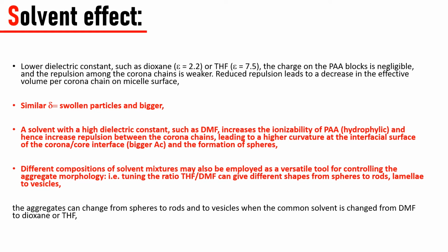However, a solvent with a higher dielectric constant, such as DMF, leads to an increase in the ionizability of the polyacrylic acid, increasing the repulsion between the corona chains, leading to higher curvature at the interfacial surface of the corona-core interface, and the formation of spheres.